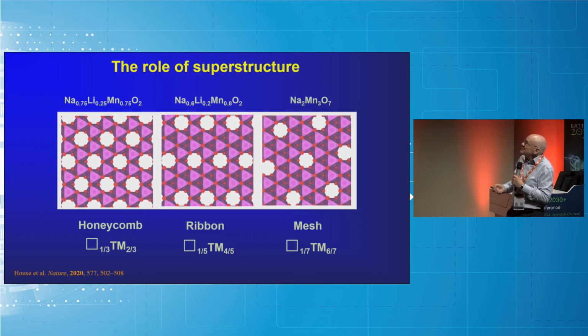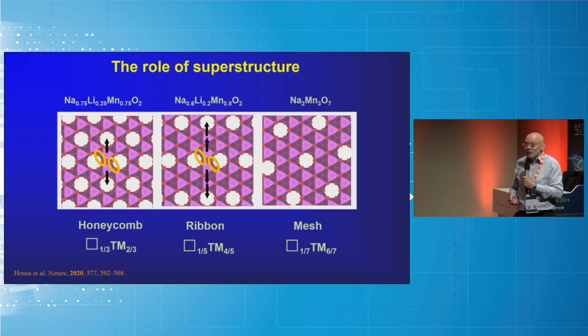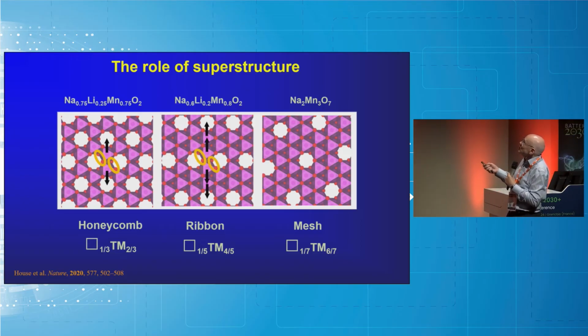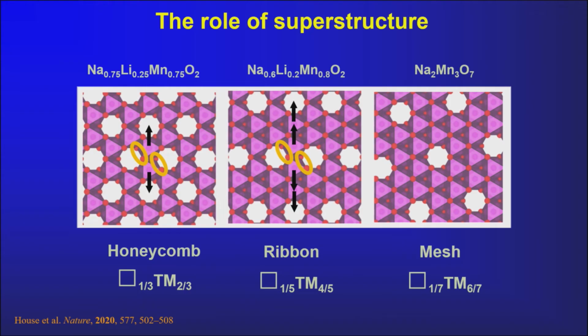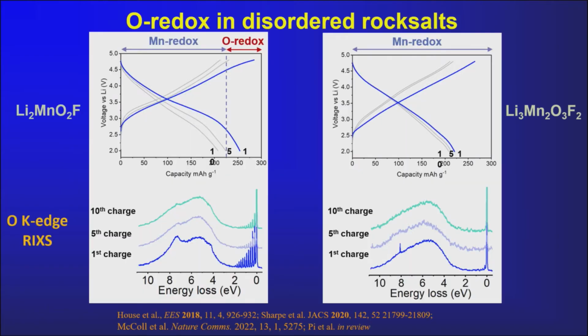And the reason this happens is that's the process that occurs in our honeycomb, the rearrangement, harder to do in the ribbon, and also harder to do in this one here. So this is why this suppression occurs. It's harder to reorganize these transition metal ions to trap O2.